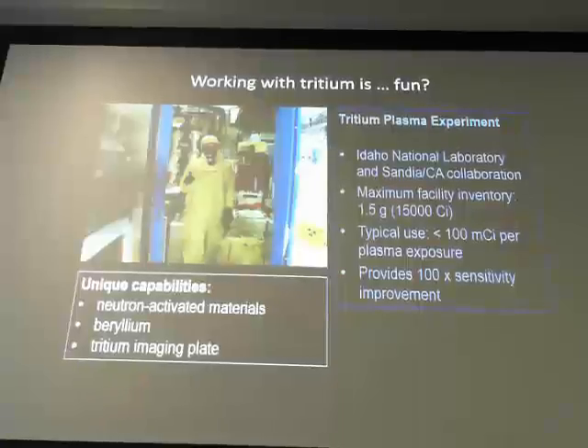There's a program ongoing, a collaboration with Oak Ridge National Lab, where we have samples exposed in the HFIR reactor, and then they're taken out of the rabbit and allowed to cool for a number of years, and then we do plasma exposure in here, and then do analysis of the trapped tritium and deuterium as a result. We can also look at beryllium in this device, and we have tritium imaging plates, so we can do some depth profiling and look at surface contamination of materials as a result.